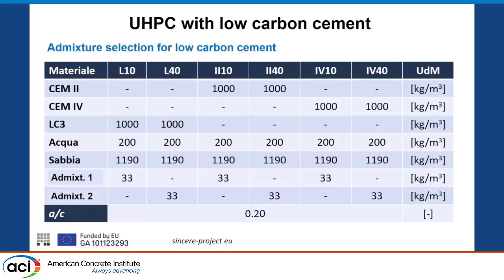We went from this and we started to say, okay, let's try to use CEM II. CEM II, according to the European classification, is a limestone blended cement, limestone filler. CEM IV is with pozzolanic cement. And we also had some non-commercial produced LC3 with limestone calcined clay. So, sorry, the words are still in Italian, water and sand. You can see that the water binder ratio is 0.2 as typical.